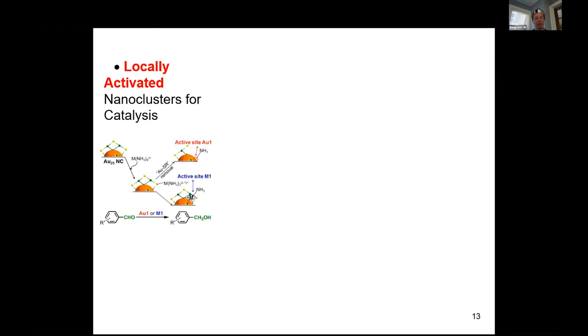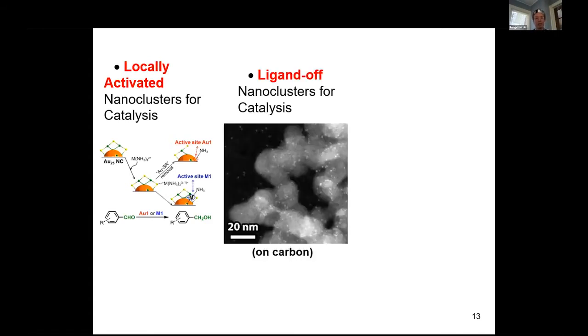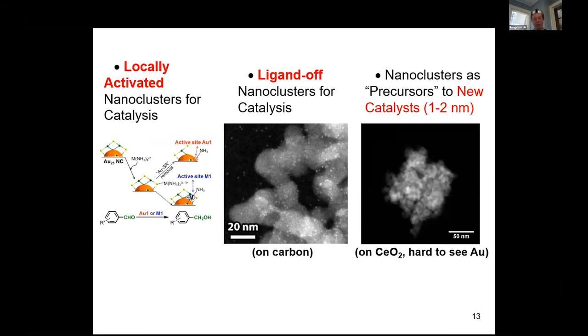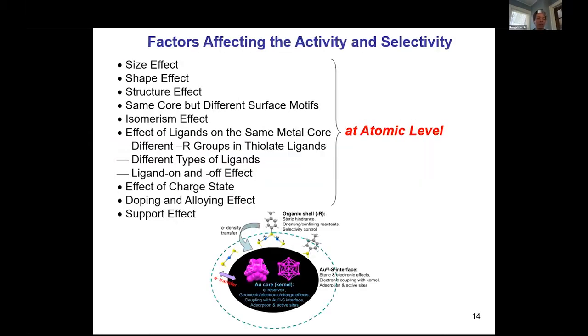So in this case, you can, for example, kick out 1 or 2 surface ligands to fully expose the surface site. And then, of course, if you really hate ligands, you can kick out all of those ligands by thermal treatment or some other redox treatment. And then finally, you can also utilize these nanoparticles to make new kinds of nanocatalysts. So these are the different ways you can utilize atomically precise nanoparticles. With these well-defined systems, you can really look into some very fundamental issues, for example, size effect and structure effect at the atomic level.